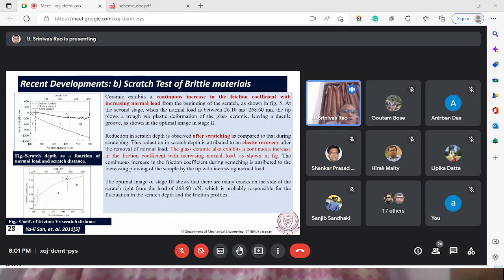So this is the scratch depth as a function of the normal load and scratch distance. We are increasing the normal load. After a certain duration, we get the transition, and because of the micro crack formation, a lot of vibrations are happening. Another important aspect is the coefficient of friction versus scratch distance. This test shows that the coefficient of friction is also gradually increasing. There is a continuous increase in the friction coefficient with increasing load.